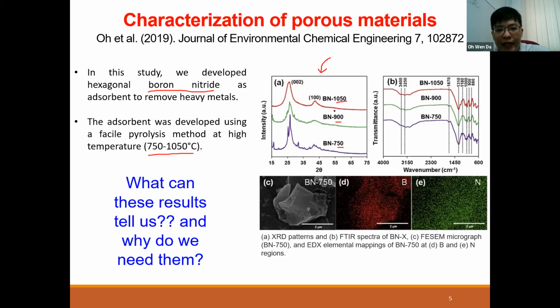So once I get this XRD pattern, I compare it with the library, and if I have boron nitride, I will have two different peaks at 002 and 100. So you can see here for this 1050 boron nitride, we have these two peaks, which means that at 1050 I have boron nitride. I've successfully prepared this. If I change the temperature to 900, I also will have these two peaks, this peak and this peak. If it's 750, same thing, I will have this one and this peak.